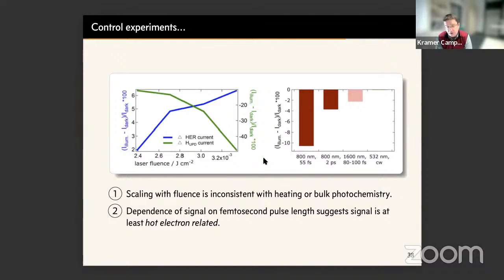We also now tried to repeat the same experiment with longer pulses at 800 nanometers, with different photon energies, and with CW radiation. And what you see quite clearly is that the size of the signal we observe depends really critically on the length of the pulse. So it's this few femtoseconds, the shorter the better, and that it's a bit sensitive to photon energy, perhaps, right?